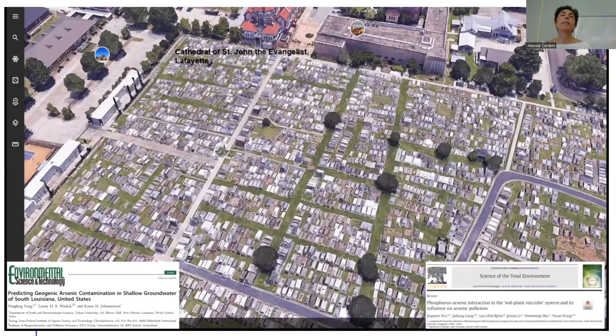The other area is another study, from the Cathedral of St. John the Evangelist here in Lafayette. The point is that this study started from one of my past courses. Some students sampled the graveyards of this church. They found a high amount of arsenic. The origin is geogenic, but it's possible to use phosphate and phytoremediation to reduce the mobility of the arsenic, in particular if it is arsenic 5+. If it is arsenic 3+, phosphate means remobilization of arsenic,